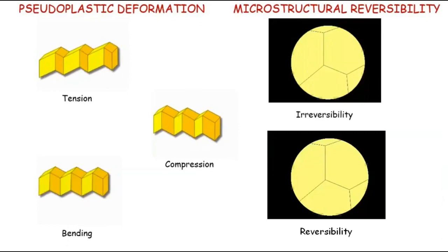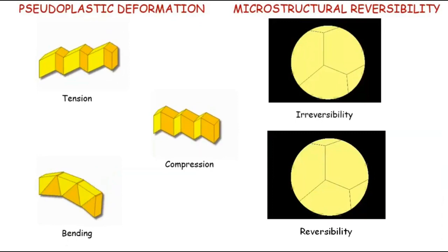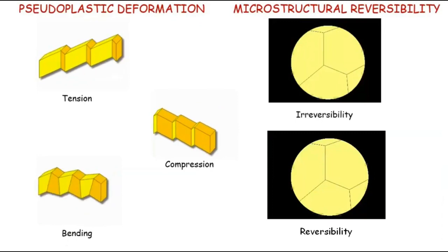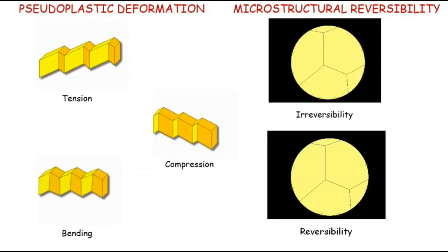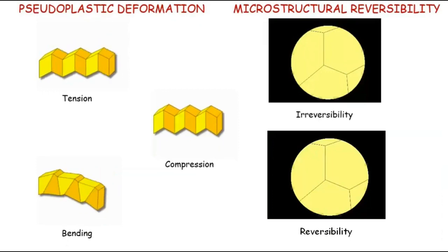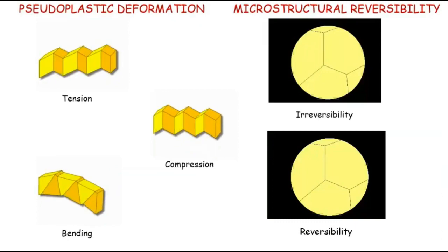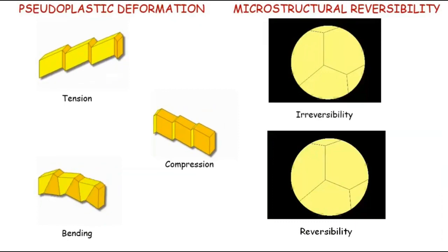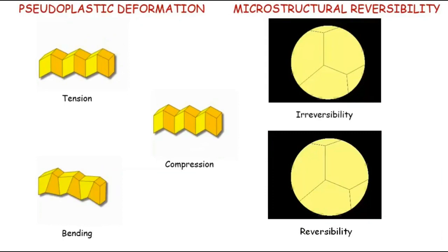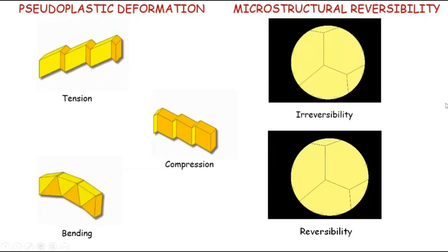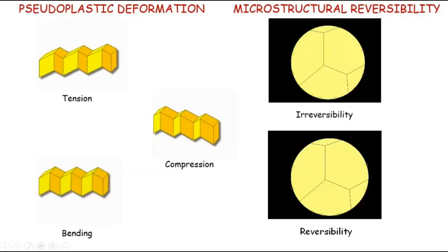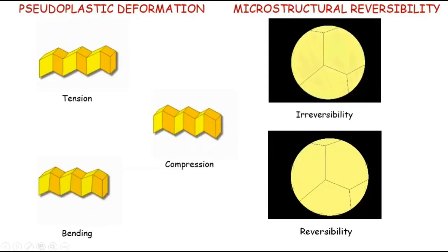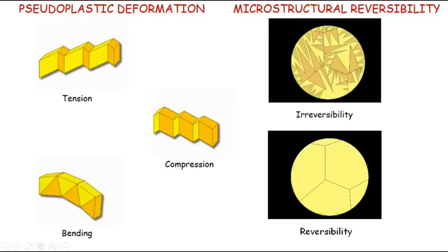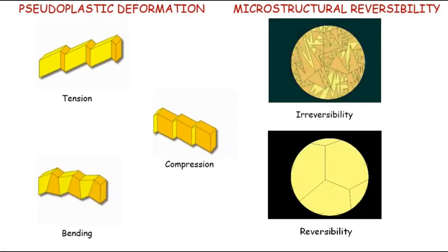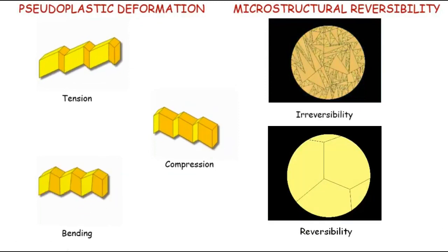And if you start with the 24 variants, then they will cancel the shape strain, and you'll get essentially the same shape that you started off with before you cooled it. But when you do this deformation, you're getting a macroscopic shape change because you've got some variant which, in volume fraction, is more than the other. So its shape strain will express itself, and that is seen as a macroscopic shape change. And when you heat it, however, if it were an irreversible material like any normal steel,